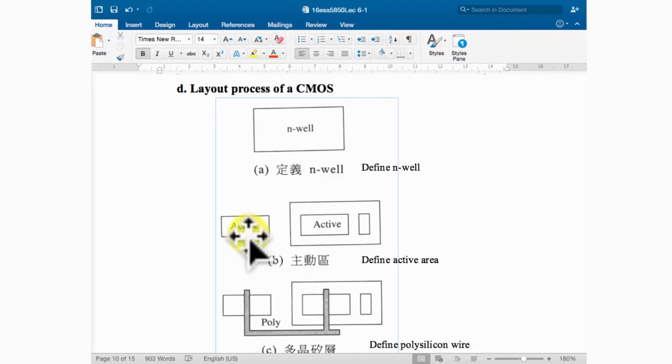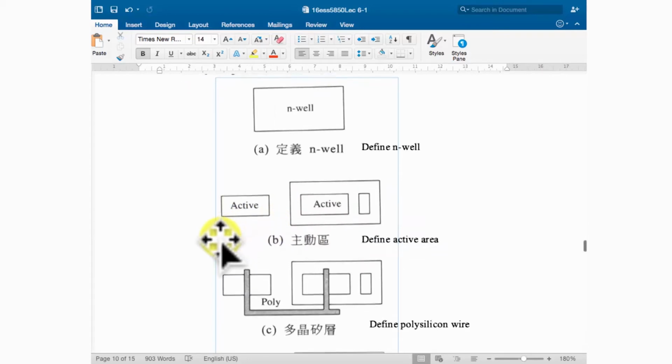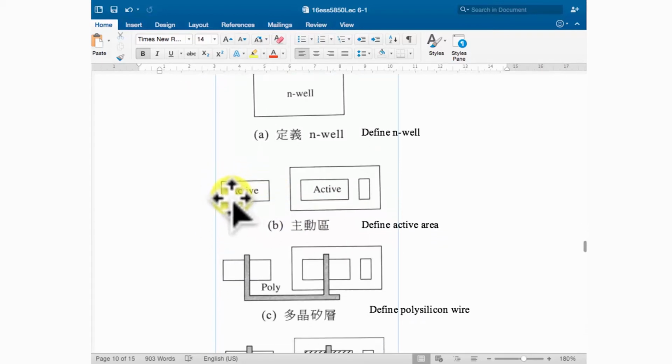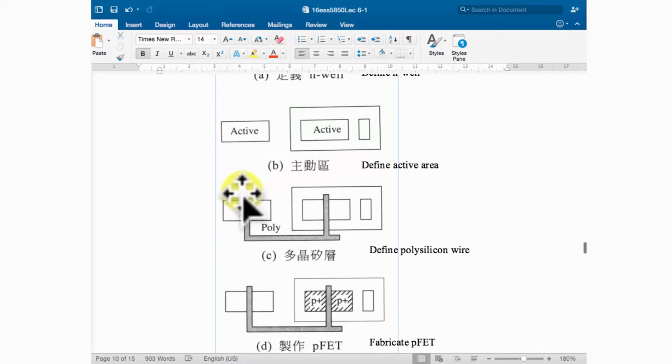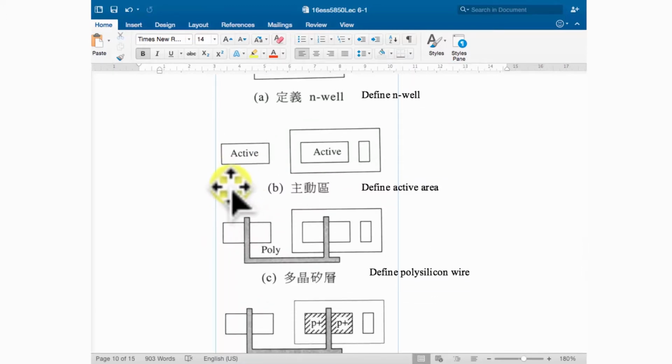So no thermal oxide here. Outside we have a thick thermal oxide. This region we call the active region. After this, you also need to take out the silicon nitride. Then grow a very thin layer of thermal oxide, less than 10 nanometers, as an insulator. Then we deposit polysilicon on the top, and then pattern the polysilicon in the gate area. So there's a defined polysilicon wire.